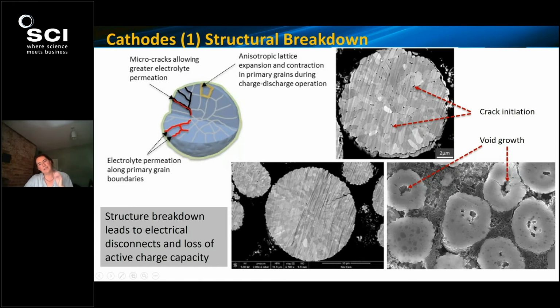And so when you start lithiating these structures, you get anisotropic lattice expansions and converse contractions that can result in microcracking, because a lot of strain can develop when these things are expanding in different directions. And this can actually allow electrolyte permeation along these grain boundaries, which we'll see in the next couple of slides will have another degradation mode.